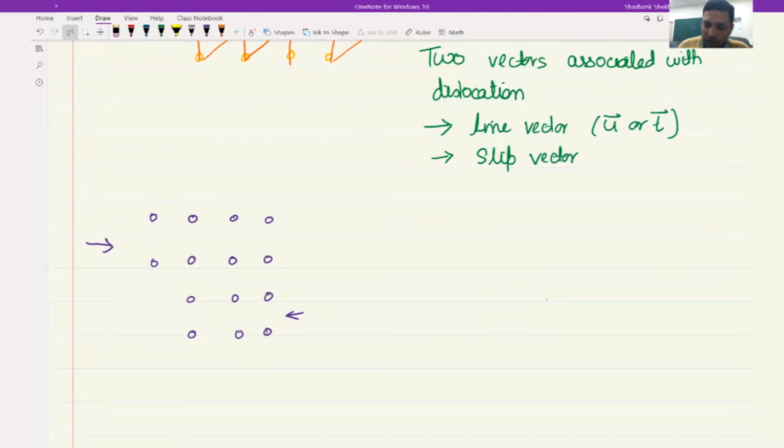Then when you have applied stress, this layer of atoms now gets bonded to this one, and this becomes the unbonded layer, and these two remain the same as before. But since you keep applying the stress, this will hop again. Now this will get bonded to these layers, and again remember, when I show you one atom, it is actually a row of atoms.